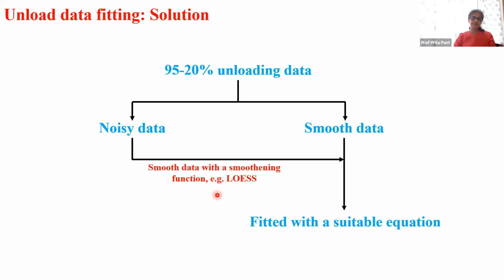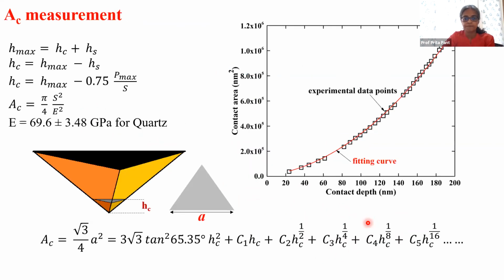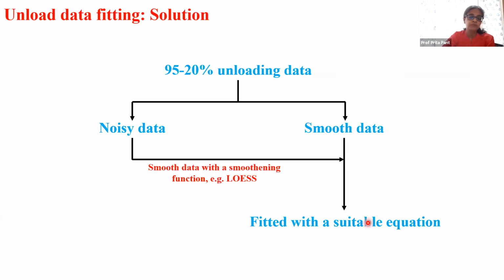We've looked at a few. LOESS is one. There is some other algorithm, Savitzky-Golay, which we have used, which gives reasonable results. So some processing may be done and then fitted with a suitable equation, I'm saying, because the original proposal was power law. Okay. But if you're still running into errors, you may want to explore, say, polynomial fitting. There's nothing very sacrosanct about power law.